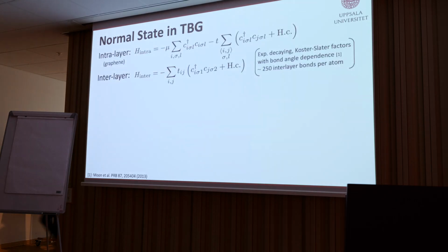Okay, so how do we model this? Well, we can take an effective model and model the A sites and do some effective modeling. We have to make sure we get the appropriate bands and appropriate topology and so on. But instead of being a little unsure which approximation we do, why don't we actually model all the carbon atoms in the system? So that's what we set out to do.